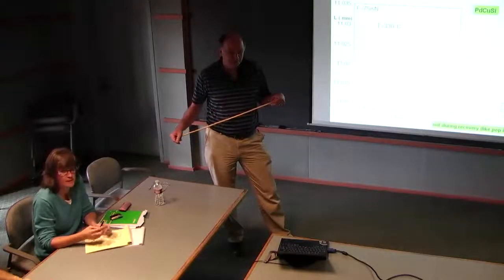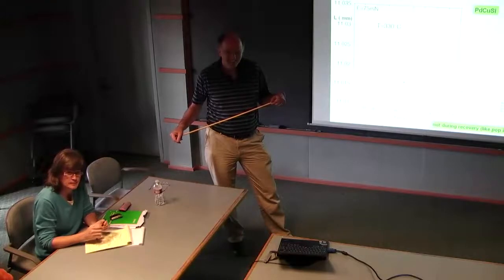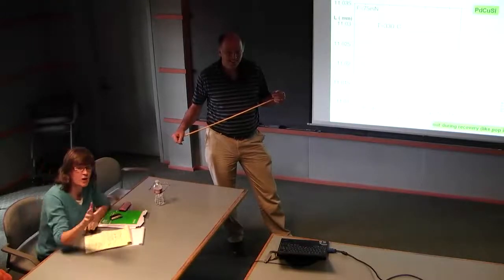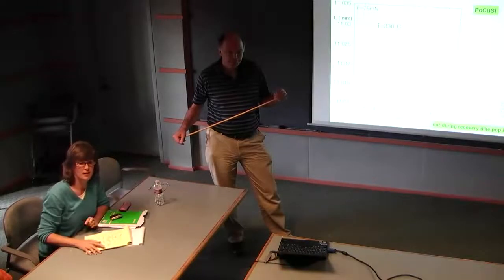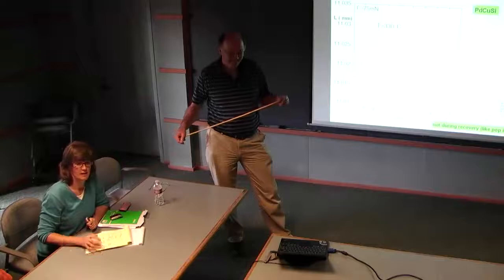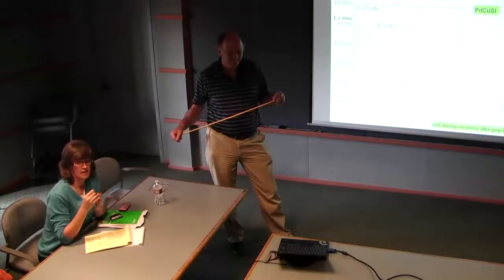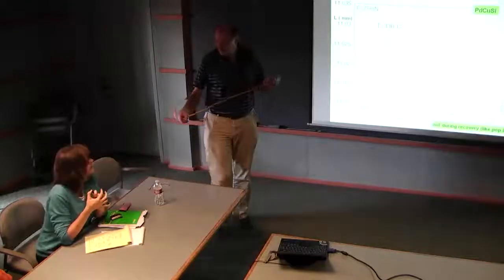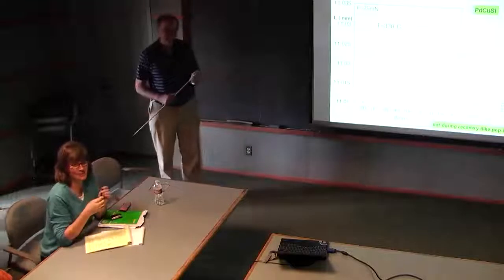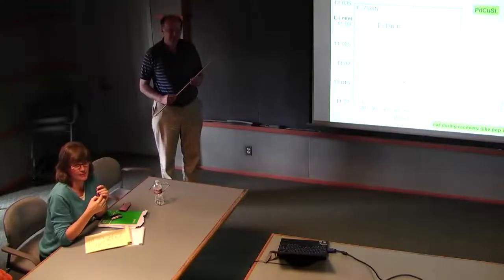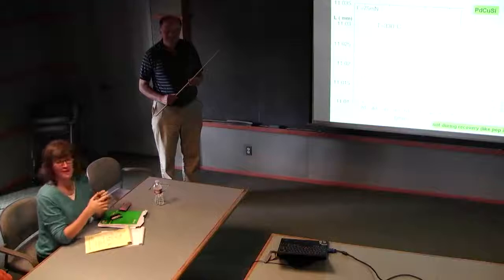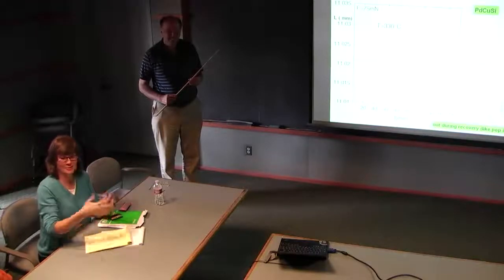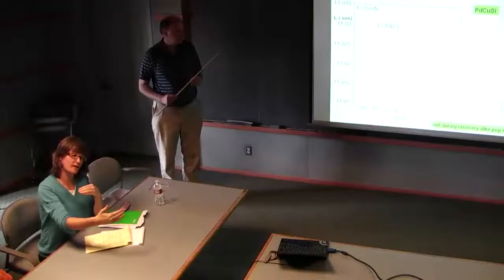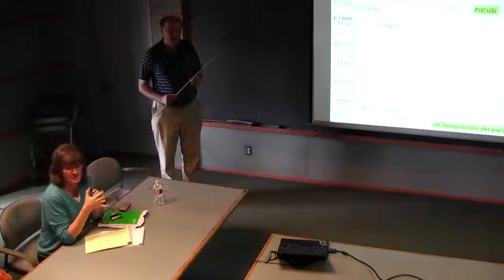Yeah, but the point is that you have this interesting observation, and it tells you it's a Barkhausen noise. It's nothing to do with that. It's not obvious. I mean, we have to run a simulation with the mean field process, and then there's a coarse graining step in there, and then one has to resample this and check what comes out. I didn't do this exercise. We talked about that already a year ago. Well then, if you present this data, you need to check that this has anything to do with it, at least with this mean field process. I think it's perfectly legitimate to show the results and to say that intuitively you might expect waiting time statistics to relate.